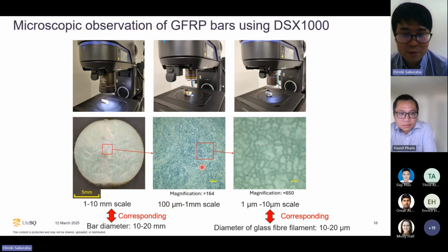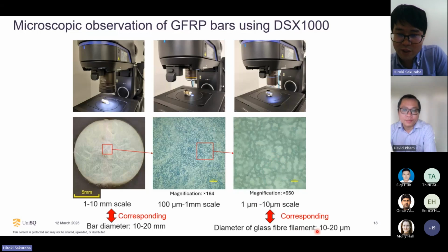So we can observe the interface between the glass fiber and resin. And we can use even higher magnification. This is 1 micrometer to 10 micrometer scale. So we can clearly observe the interface between the glass fiber and the resin. And the diameter of a glass fiber filament is between 10 to 20 micrometers, so this corresponds really well to observing the interface of glass fiber and resin.